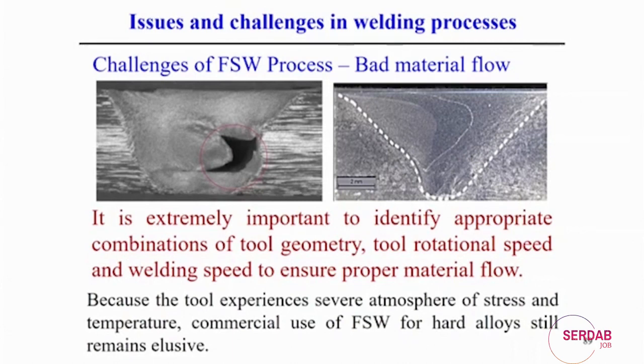On the other side, a limitation of this process is that the tool experiences severe stress and temperature. So wear of the tool is very important, and the cost of the tool is also an important matter in this process. And of course, the process is limited: if the material is very hard, it is very difficult to weld with this process. So it is still not commercially used for welding very high hardness material. In that case the only solution is the fusion welding process, but in a few cases this solid state process gives a good weld joint, and difficulties such as porosity and cracking can be avoided.